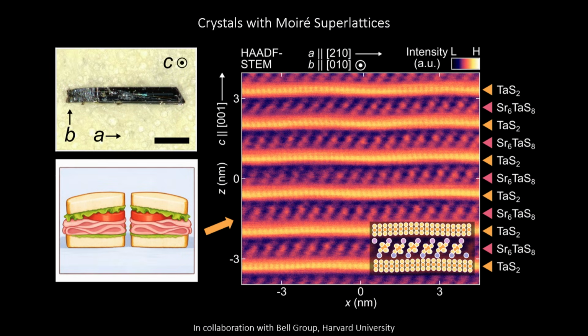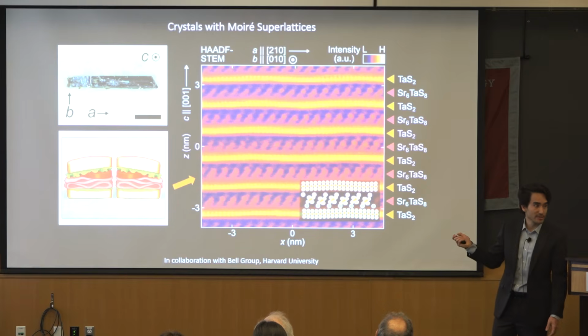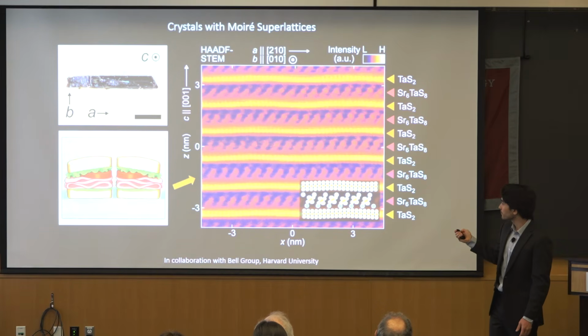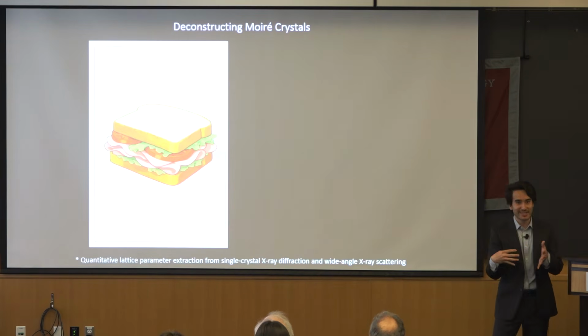And so this produces a lot of stress that's relieved in the crystal in the form of a Moiré modulation, in exactly the same geometry as we see in 2D Moiré materials. And so you can see this modulation of about 3.5 nanometers. This is exactly the Moiré superlattice. And this is a direct image of it in this crystal. So this is a good perspective, this side profile.